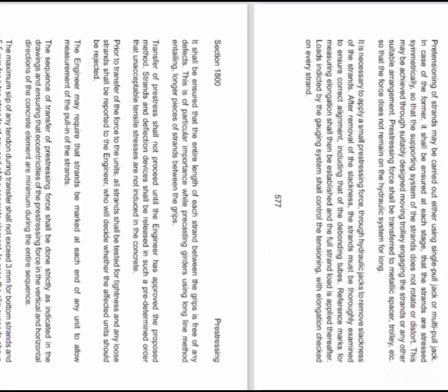It is necessary to apply a small pre-stressing force through the hydraulic jack to remove slackness of the strands. After removal of the slackness, the strands must be thoroughly examined to ensure correct alignment, including that of the debonding tubes. Reference marks for measuring elongation shall then be established and the full strand load is applied thereafter. Load indicated by the gauging system shall control the tensioning, with elongation checked on the strands, to ensure that the entire load is applied.